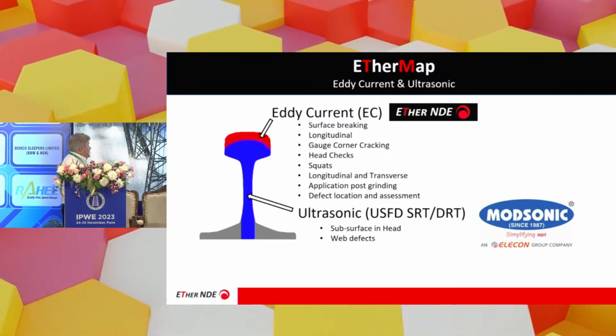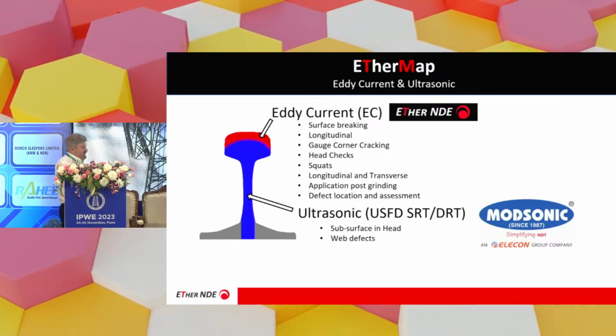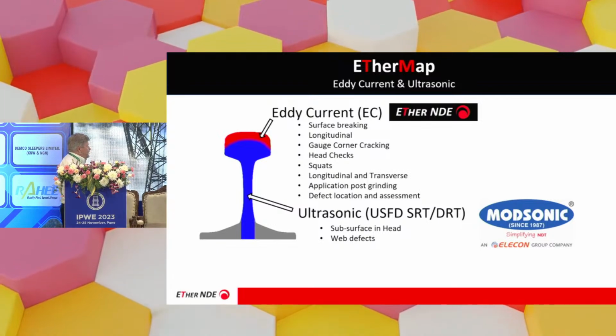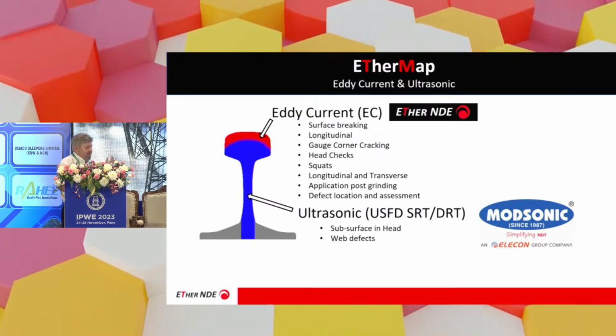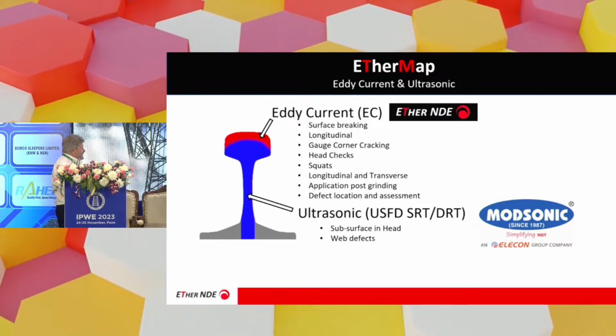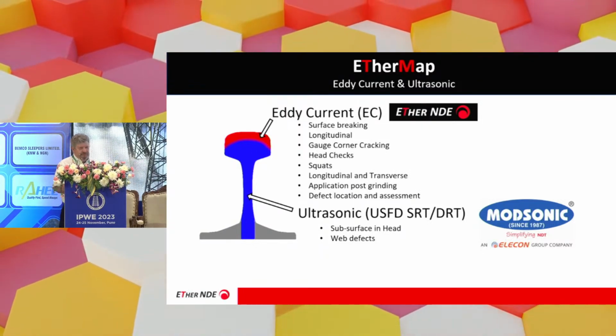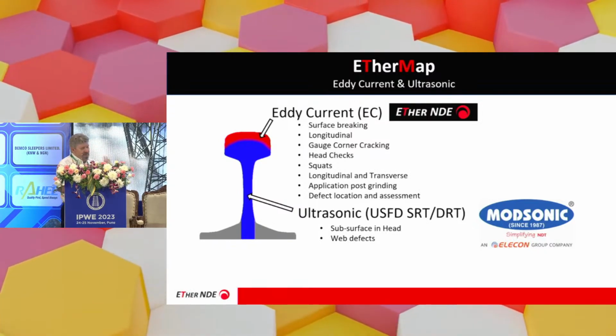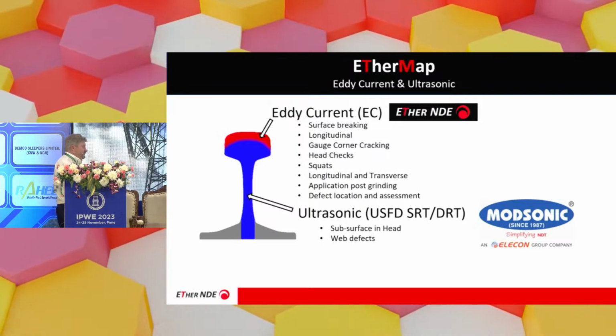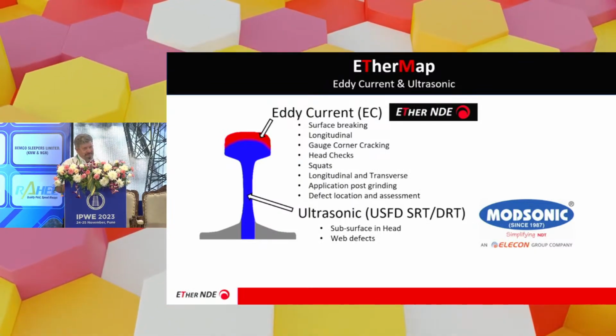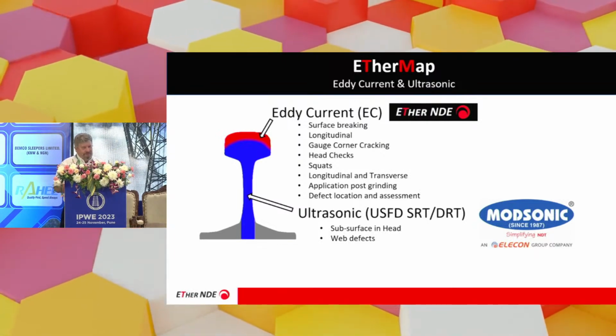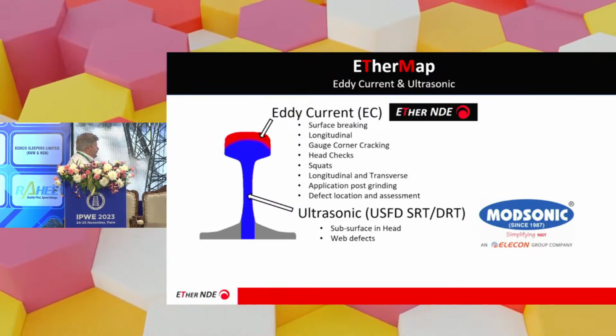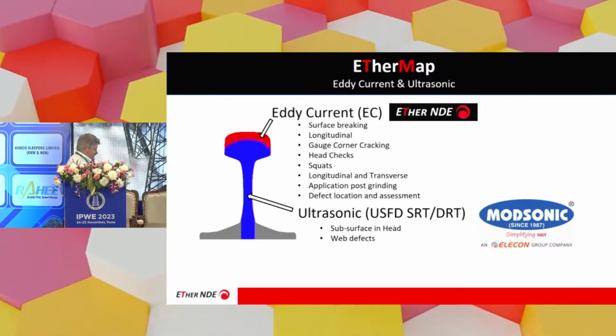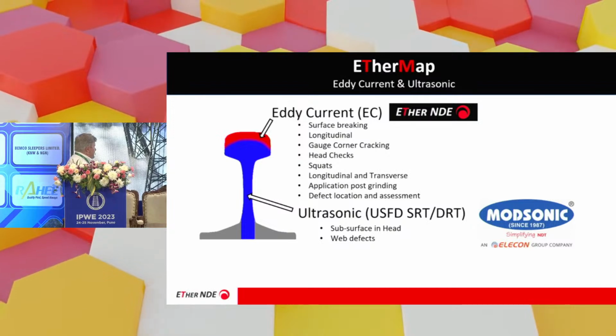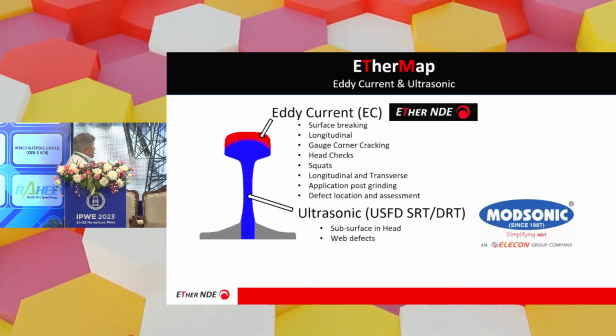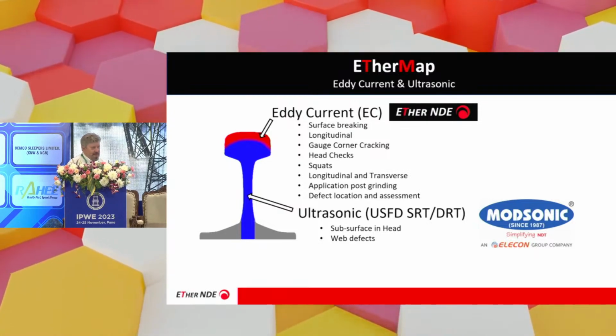We are specifically looking in the head area for defects emanating from the running surface, from the outside. This is interesting in two ways: we're getting into the gauge corner, which UT doesn't readily inspect, and we can also detect transverse defects, which UT, due to the orientation of the probes, is not very good at detecting. Those are the difficult ones to find. UT is doing all the defects in the blue area and down the web, in the head area and so on.